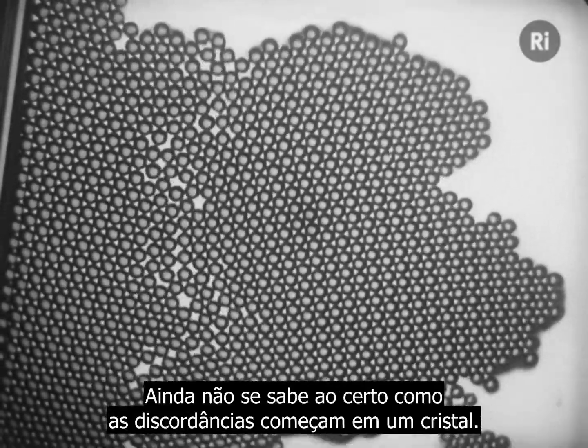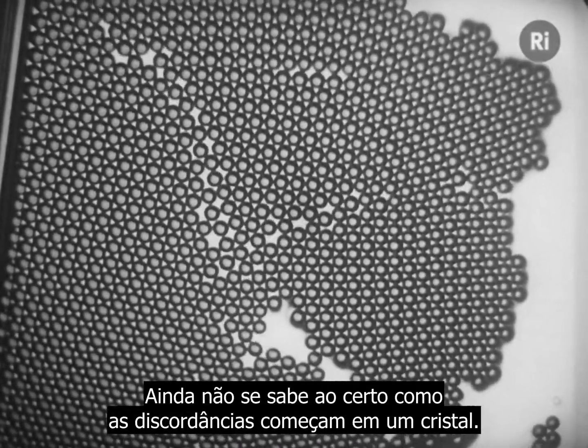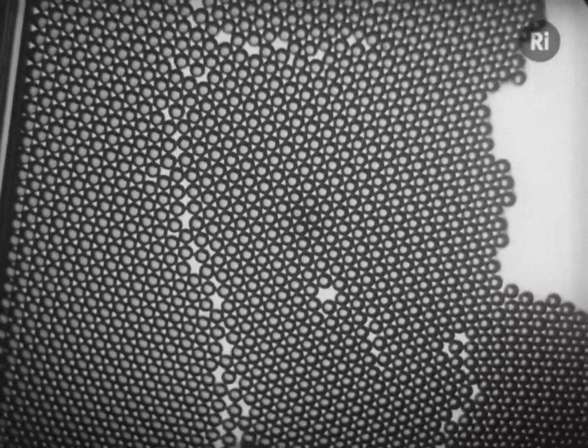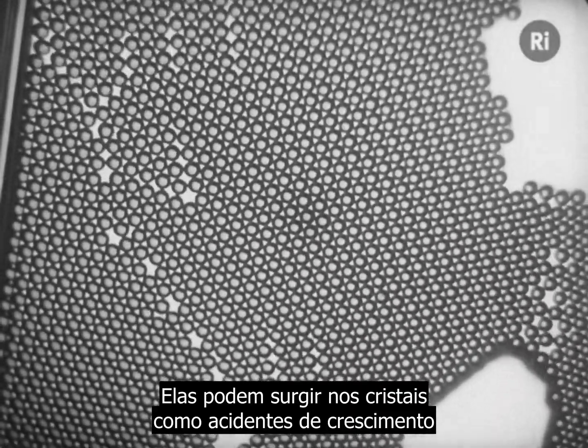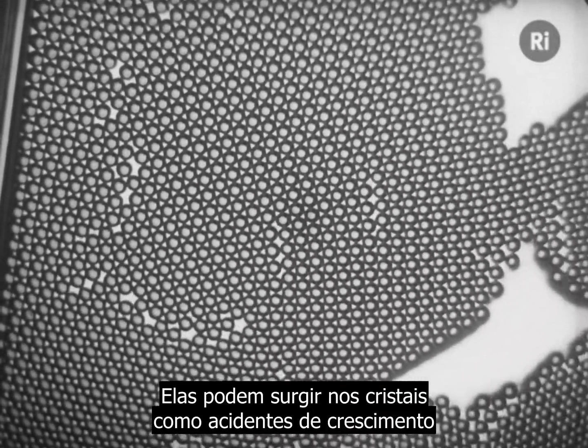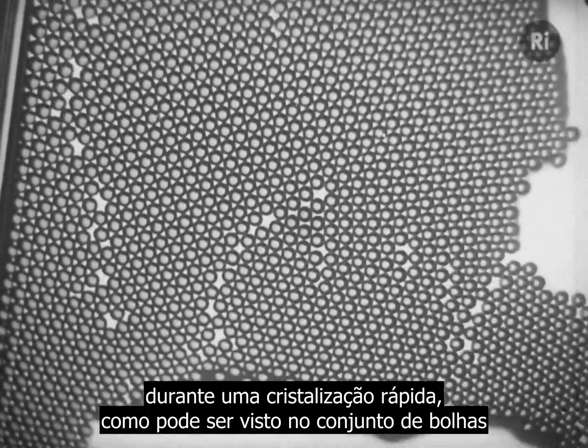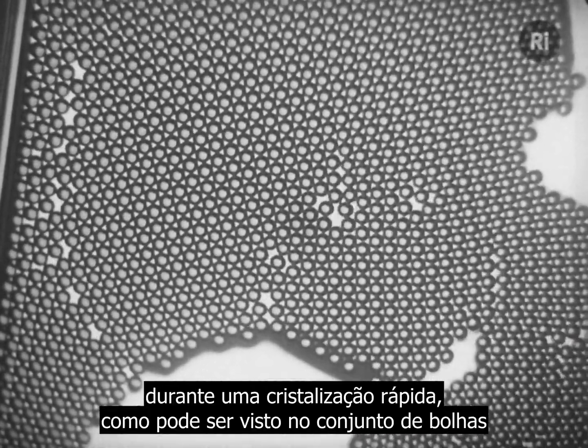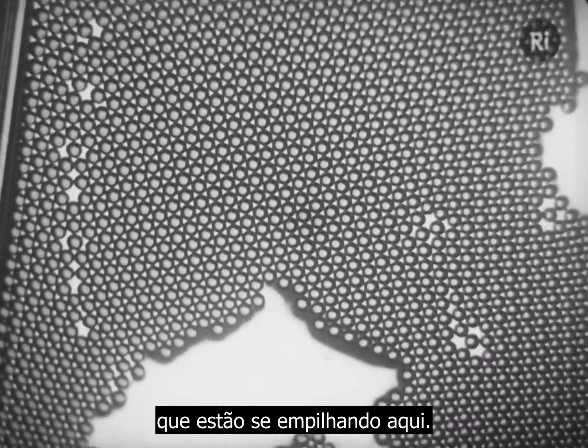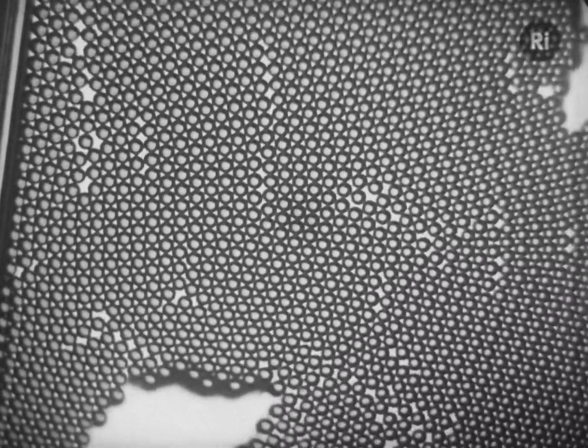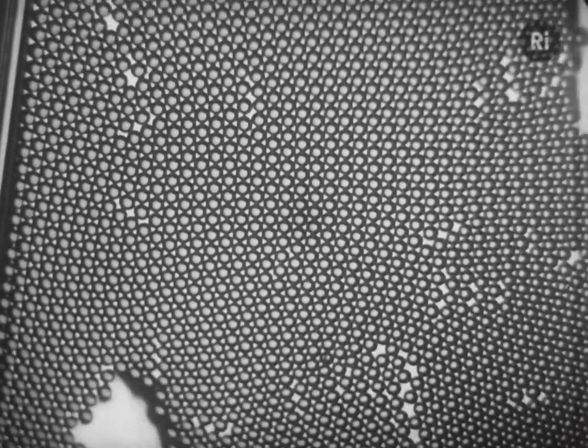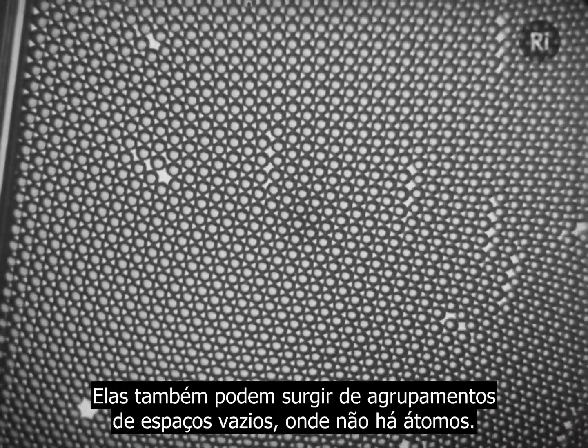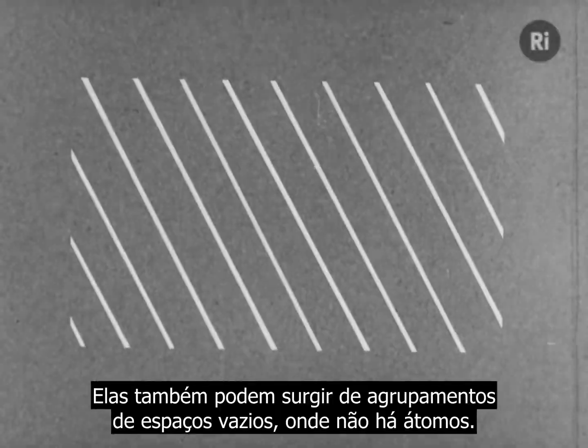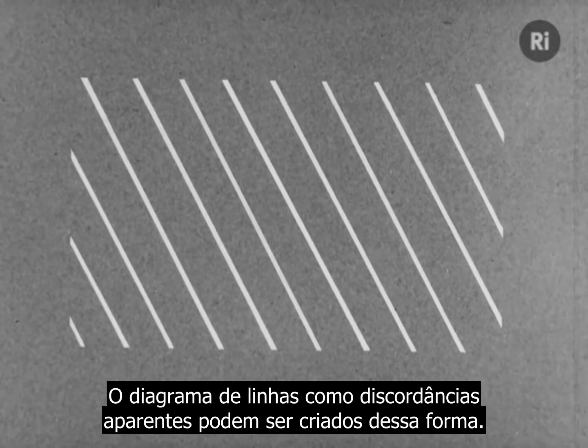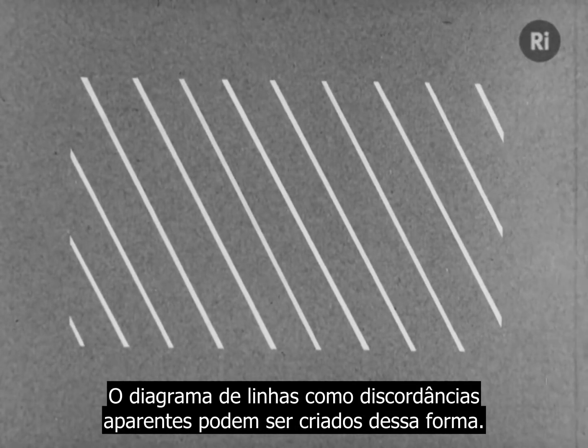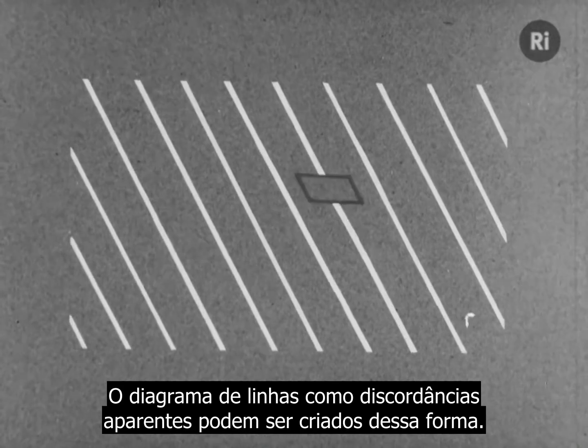It's still not certain how dislocations begin in a crystal. They may be left in the crystal as accidents of growth during rapid crystallization, as can be seen in the mass of bubbles which is building itself up here. They may also arise from groups of vacancies where atoms are missing. The line diagram shows how a pair of dislocations might be created in this way.